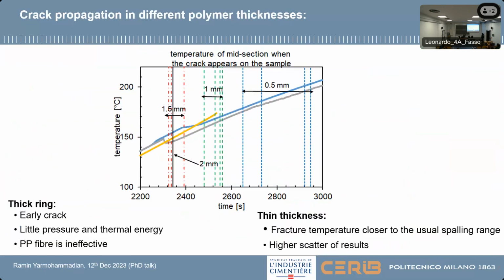So another design parameter is the thickness of the polymer which we put inside the concrete. It can change the timing at which the crack happens inside. So we started with 4 different thicknesses, and since we needed to be at a temperature of about 200 degrees Celsius, we chose the 0.5 millimeter one. But you see that there's a scattering.